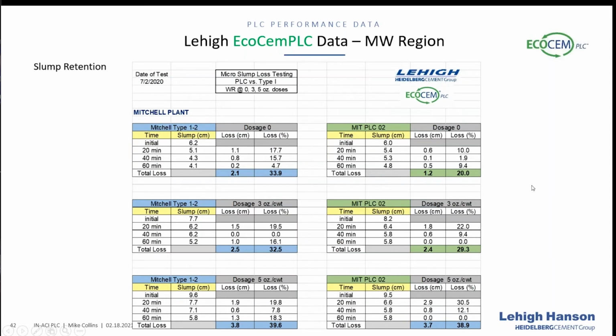So what about admixture efficiencies, things like slump retention? So we took the Mitchell cement and looked at that, looking at a different admixture dose. We did an untreated, 0 ounce per hundredweight dose, a 3 ounce, and a 5 ounce dose of a water reducer. And we did micro concrete, where we took the mini slump readings and carried that slump loss out for an hour, and then just looked at how much slump was lost.